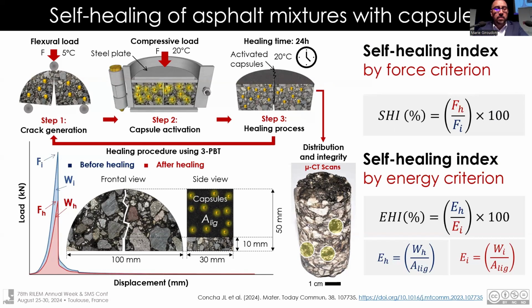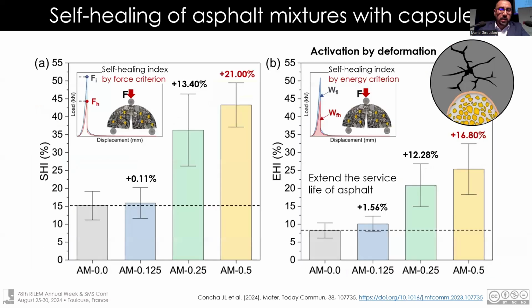After that, you can design different self-healing indexes by force criteria. You can calculate the curve, and you can calculate the area under the curve in order to use the energy, for example. But independent of the healing index, you can increase the self-healing inside the asphalt mixture. Please remember, the bitumen is a self-healing material itself. For that reason, you always need to compare your results with the materials without additives. In this case, we can increase the healing index by up to 20% compared to the asphalt mixture without capsules. When you use, for example, the self-healing index using force, this result can change when you compare it with the energy.